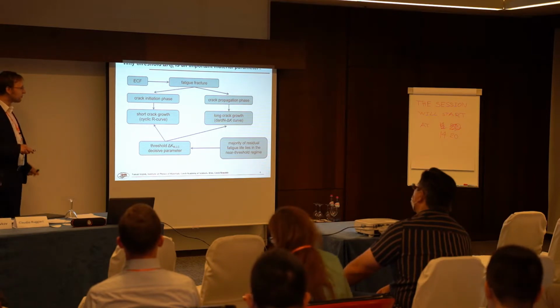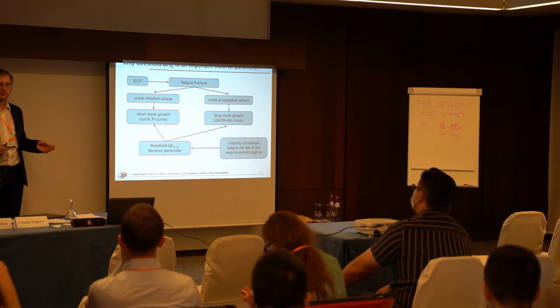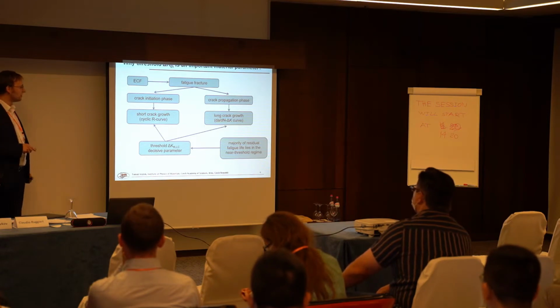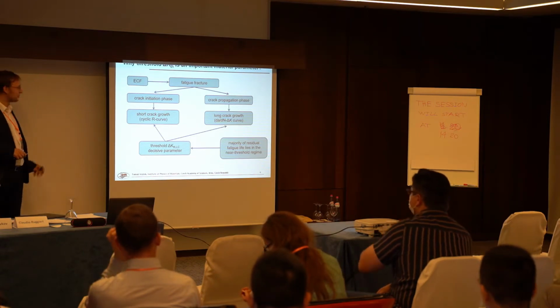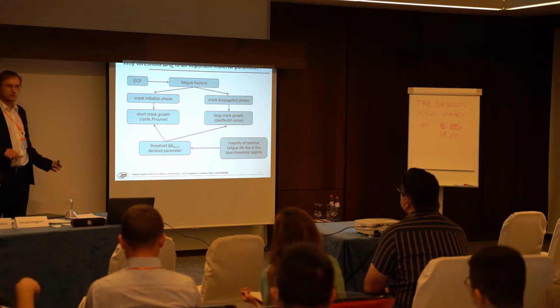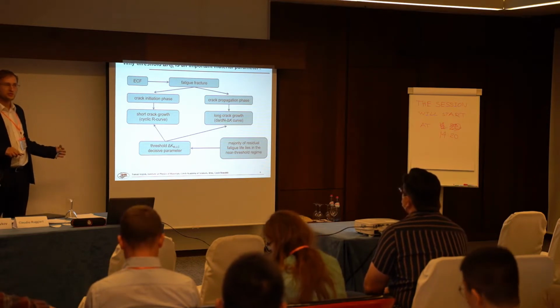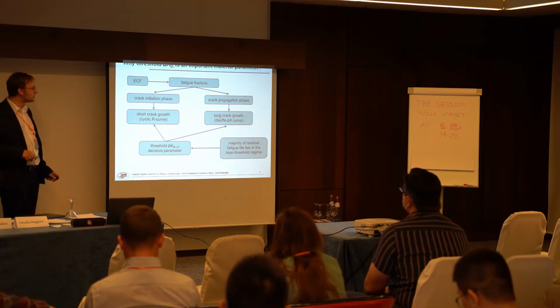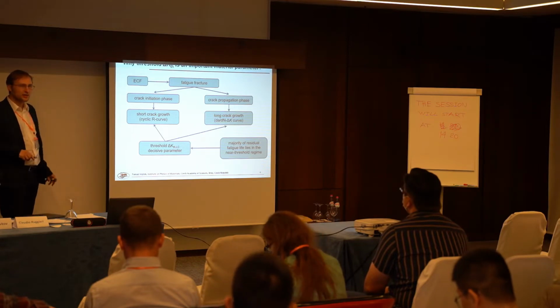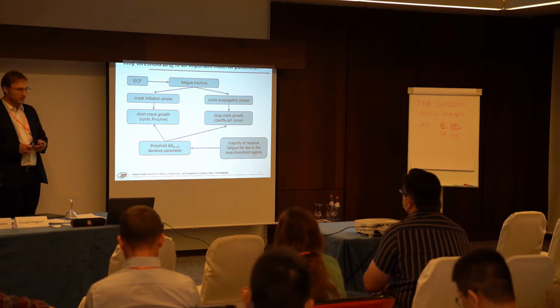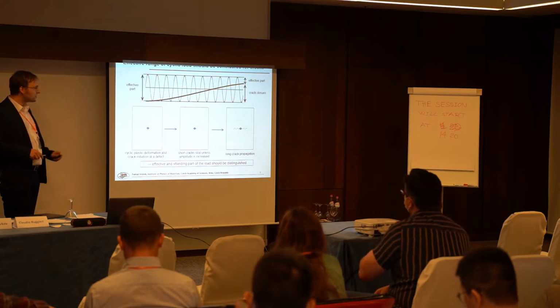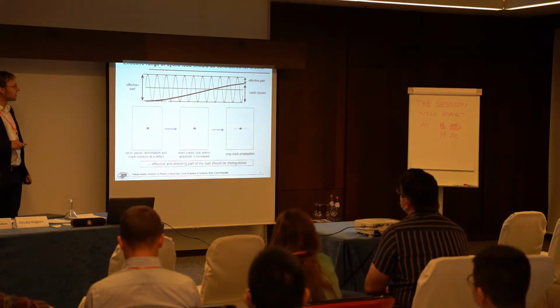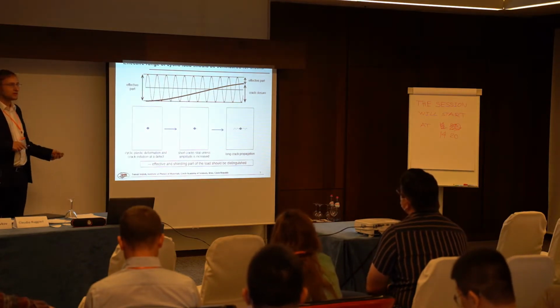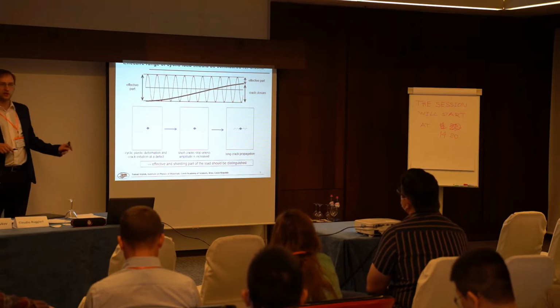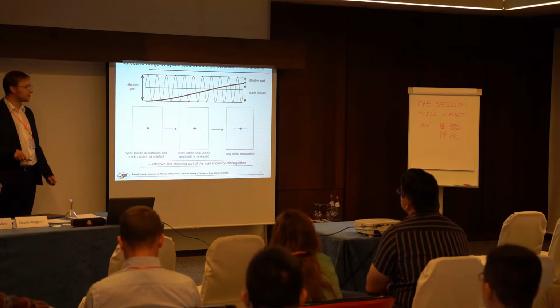And in both short and long crack growth, the threshold is the controlling parameter for the distribution curve. So that's why we think that the long crack threshold is a very important parameter, especially if we consider that most of the residual fatigue life lies in the near threshold regime. This is just to remind us that the applied load needs to be divided to the effective part and a corrective shielding part in case we have presence of cracks.